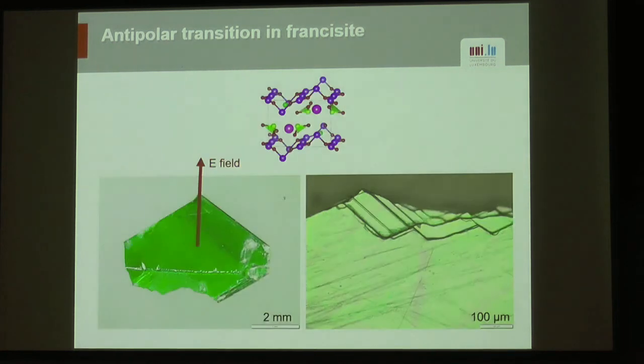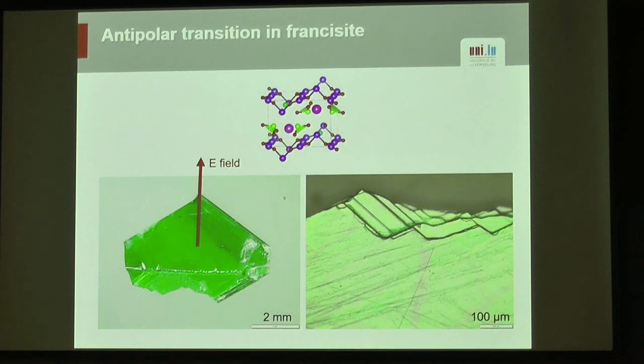We are not there yet, so I just wanted to show you what the crystals are like in real life. So they grow in this kind of very nice leaf shapes, but they are extremely thin, and you want to apply the electric field along this direction, okay? And obviously, because of this layer structure, it's super difficult to prepare, so the only thing we have achieved so far is to destroy the crystal. So rest in pieces, poor thing. We are not giving up. We still are on it, but experimentally, it's quite a challenge.